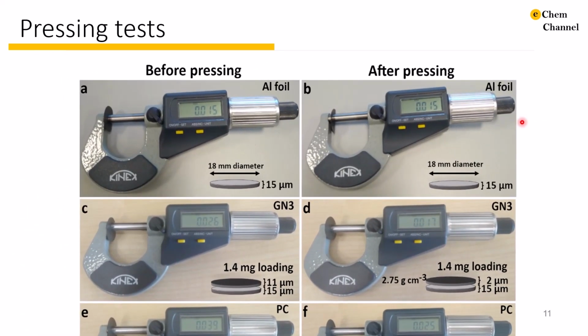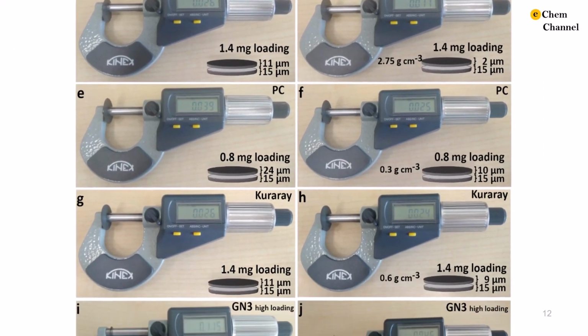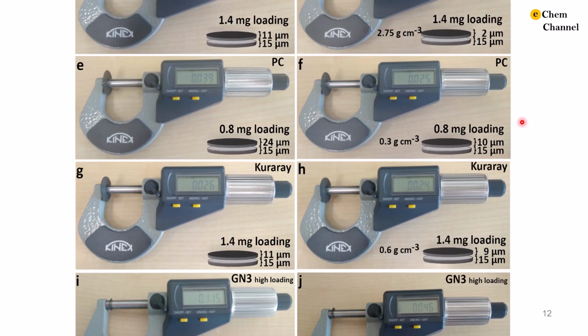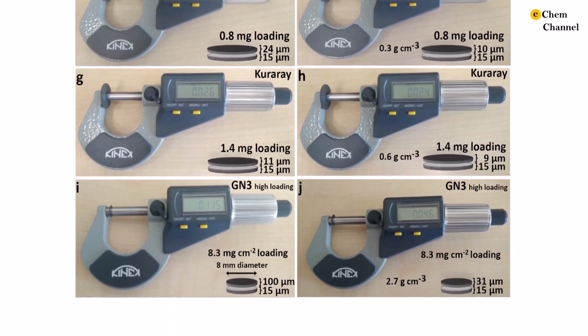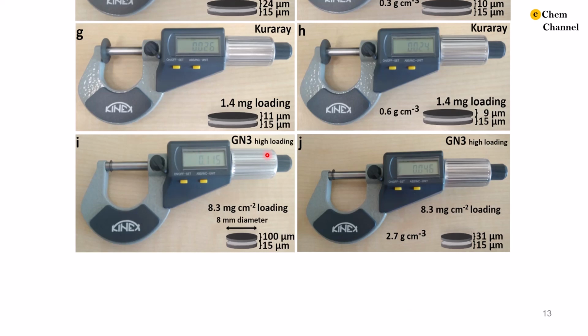First, control tests were done with aluminum foil by itself. The results verified that no compression took place for this aluminum foil. Moreover, we also performed control tests with commercial carbons of high surface area, around 2000 square meters per gram, the porous carbon and the Kuraray carbon, which is used commercially for supercapacitors. Their densities match those provided by the supplier. Moreover, we were also able to press the GN3 material at high loading to confirm that our material can be pressed to this high density even at high loading.